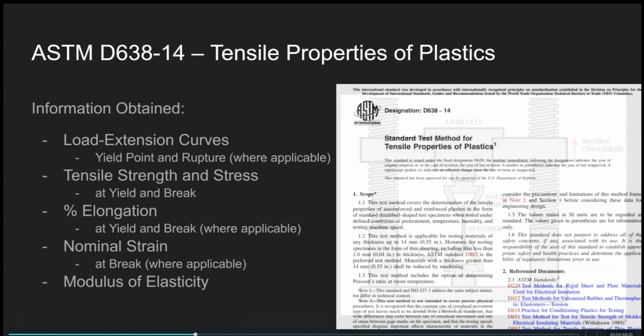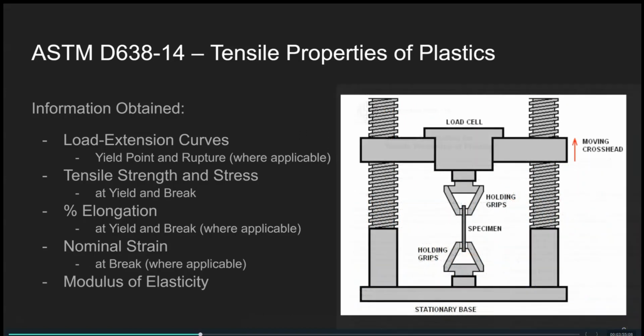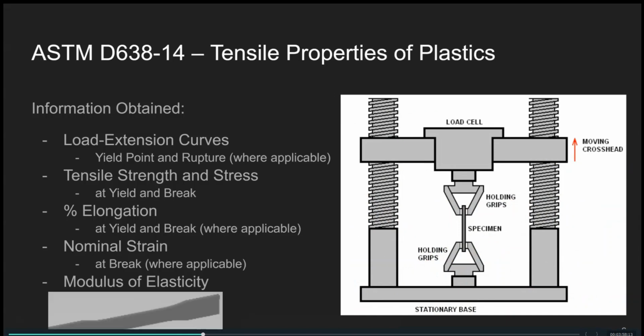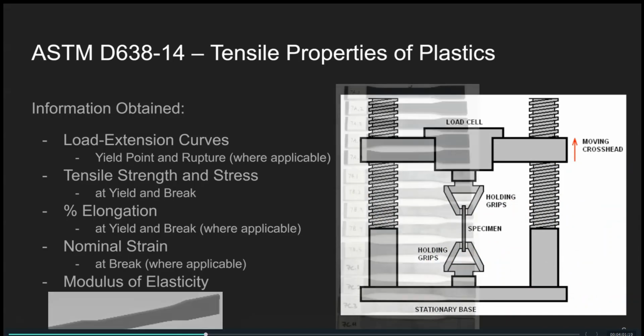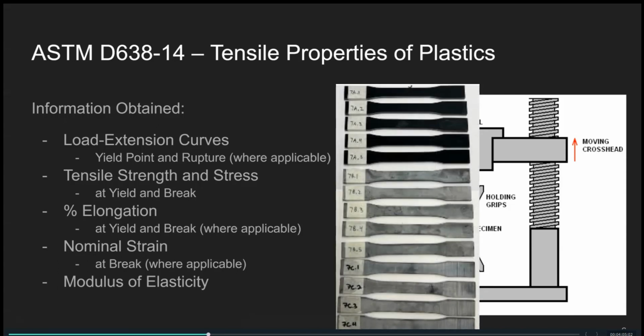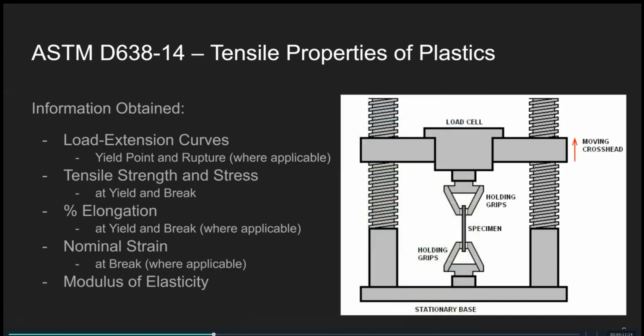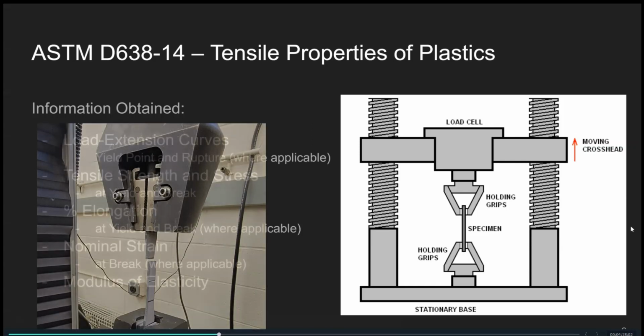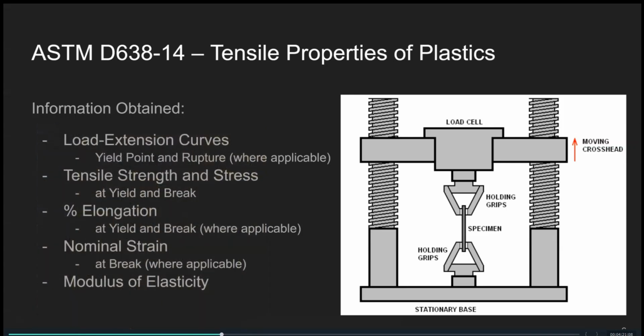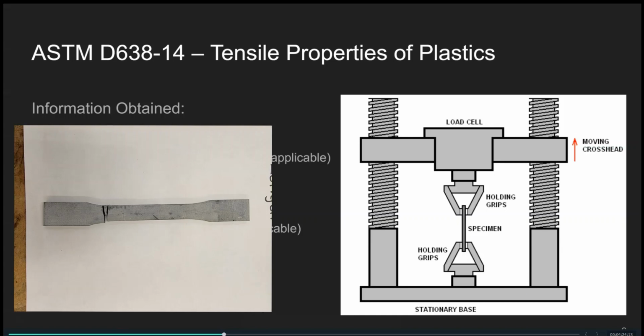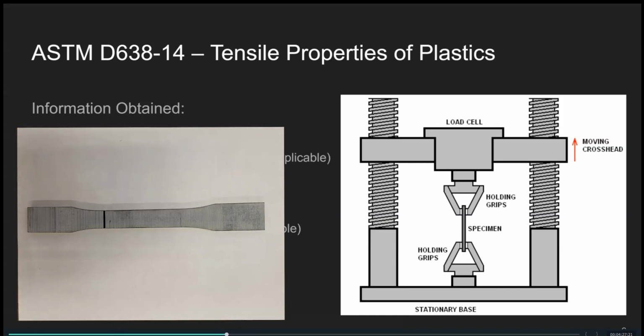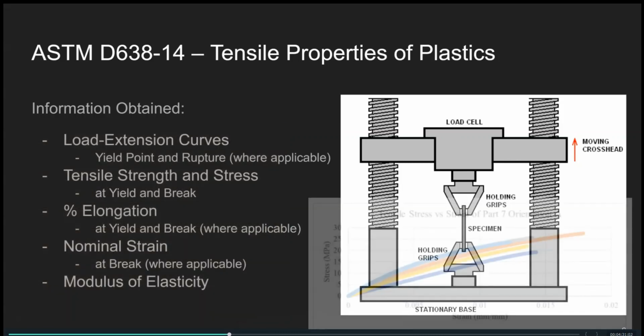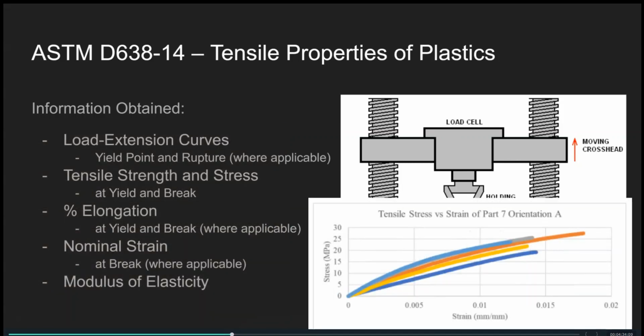Next were the tensile properties, which is ASTM D638. This is where we got the bulk of our mechanical properties of the material. Obtained information was load extension curves, tensile strength and stress, percent elongation, nominal strain, and modulus of elasticity. This testing was conducted on the Instron in the materials lab at Grand Valley State University, and we used wedge grips to fasten the specimen between the load cell and the stationary base. No yield behavior was observed, only break at rupture. So yield calculations were voided, and break was what provided us most of the data, indicating that we had a brittle material.